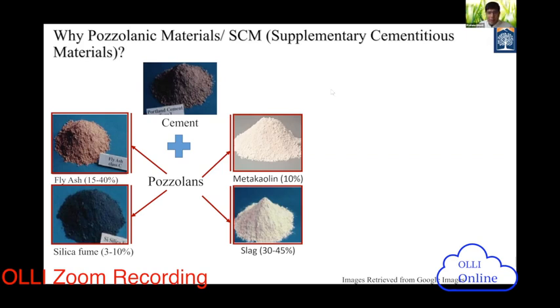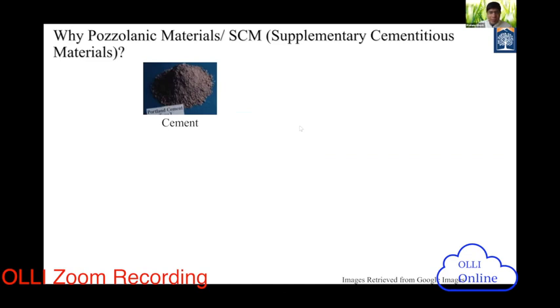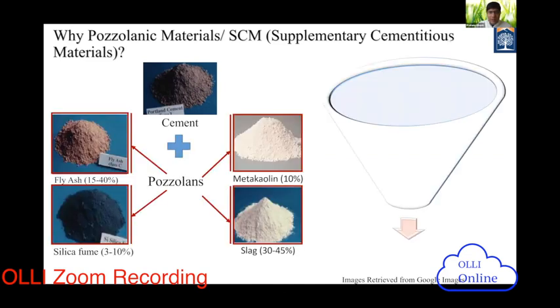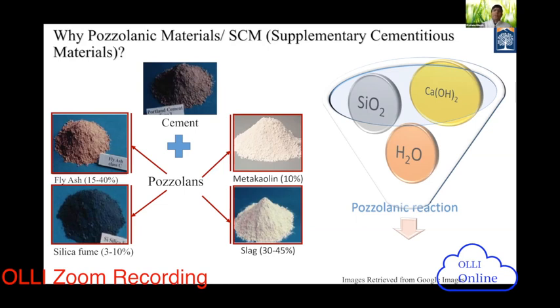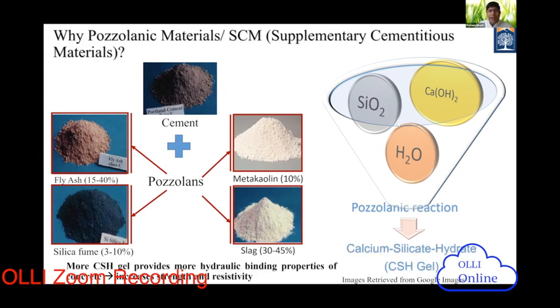That being said, now moving to the next one. These pozzolans have a heavy silica component. When they combine with calcium hydroxide and water, they undergo the pozzolanic reaction, and that makes a compound we call calcium silicate hydrate. I'm not going into the details, but we call that CSH gel. This special CSH gel provides the hydraulic binding capacity of the concrete.